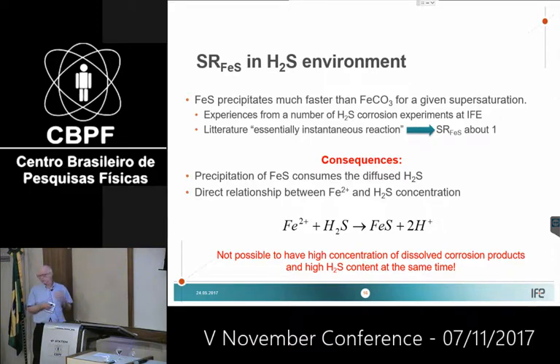But if it's controlled by CO2 corrosion, you will always have a reasonably high amount of corrosion products. And that is called the consumption model or hypothesis or theory. And it's still debated, and it can be a little controversial. But at least in experiments, we see this all the time. H2S is consumed by the corrosion product. So it's not actually H2S that corrodes the steel. It's H2S that reacts with already dissolved corrosion products.